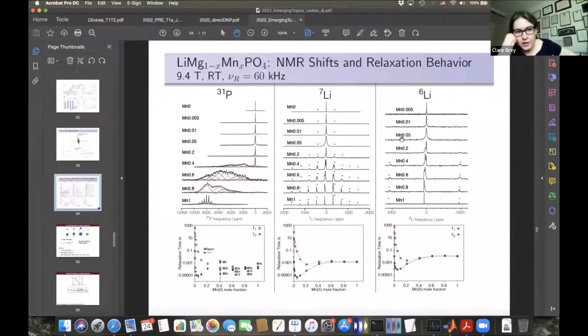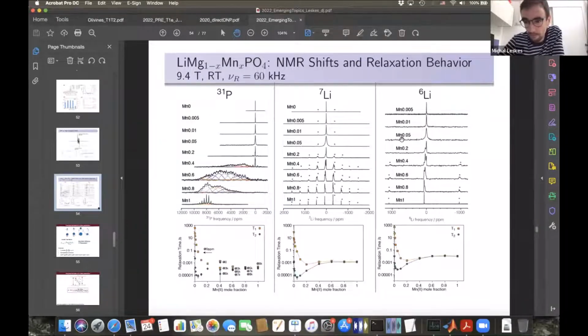And in any of these cases, did you see examples where, in the DNP, you found a regime where you selectively enhanced one of the local environments more than others? Not on purpose, but we had, for instance, cases where we had some agglomerations of metal ions. In these regions, for metal ions in a more clustered region, the electron relaxation time would drop, and the nuclear relaxation time would be fast because they are in closer proximity. For these cases, if we were on the negative side of the DNP enhancement, we could see at the beginning a positive growth of the magnetization in a saturation recovery, because those nuclei relax fast but are not DNP enhanced, and then it dropped to the negative side because of the nuclei in the regions where metal ions are less concentrated.